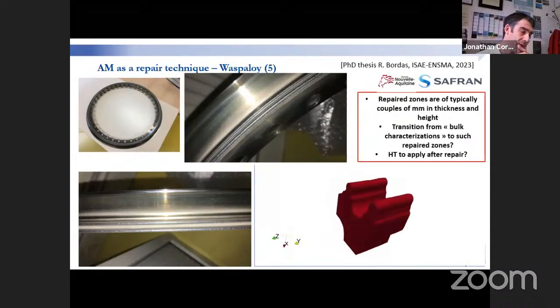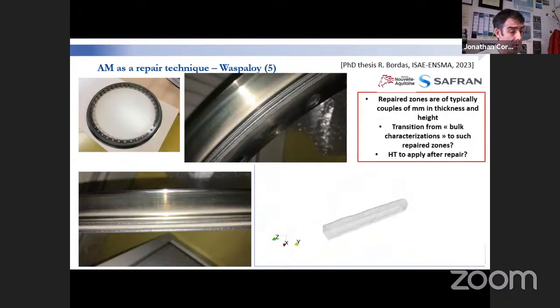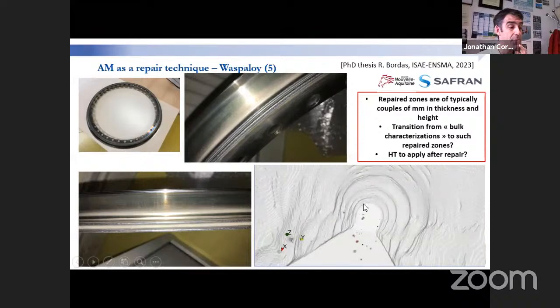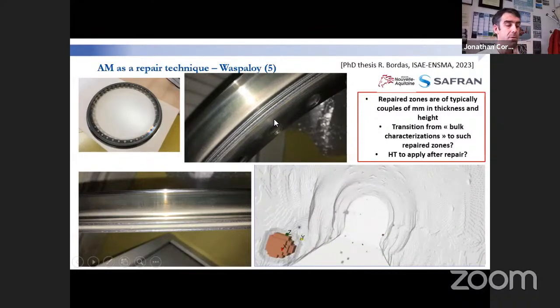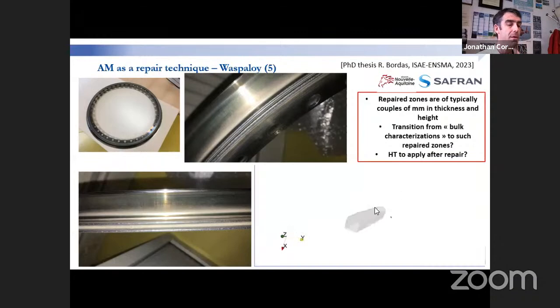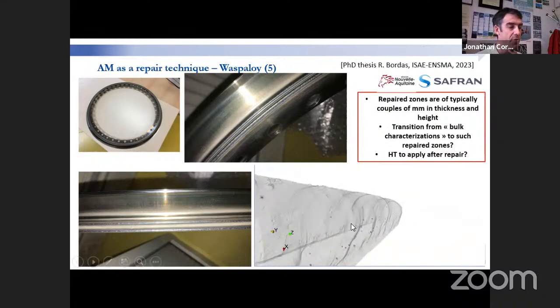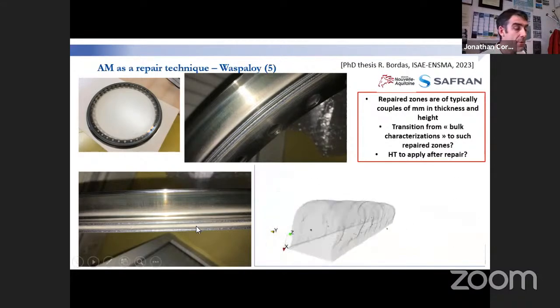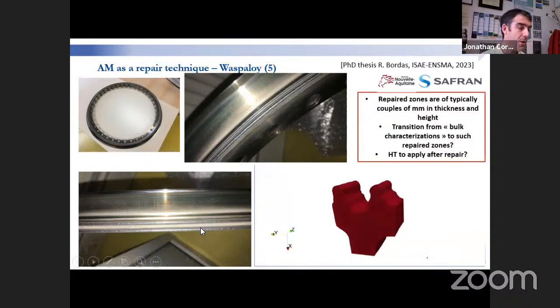And our strategy is to build walls with different processing parameters, meaning different pores, different distribution of pores, so as to try to probe the mechanical properties of those very, very small parts from which we are not able to extract specimens to do conventional creep and fatigue tests. So that's a very specific topic for which we need modeling tools to approach the properties of those parts, which are typically submitted in service to creep deformation and fatigue fretting issues.